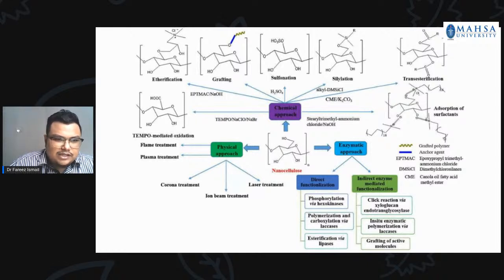For chemical, they have etherification, grafting methods, TEMPO-mediated oxidation, sulfonation, silylation, and transesterification. For physical, some are using glow discharge treatment, ion beam treatment, corona treatment, plasma treatment, as well as flame treatment. For enzymatic, it can be direct enzymatic functionalization using phosphorylation via hexokinase, or indirect enzyme-mediated functionalization. It can be grafted using an active molecule.